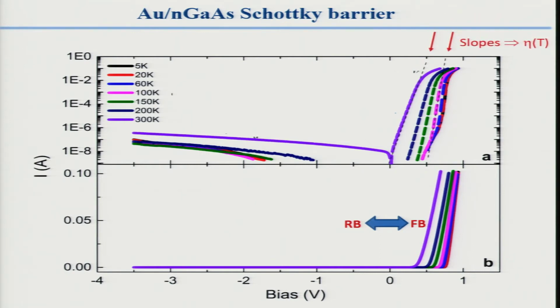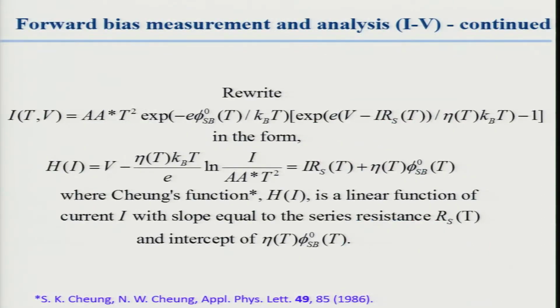These slopes from taking the log, this is logarithmic over a reasonable range, so we can extract from the slope of the log of the current versus the voltage the ideality, so we can measure that from the slope. And we get cut off by this series resistance limit. So you want the series resistance to be small. Otherwise, if it's large, you'll get cut off at a lot lower current. So we want low resistance. And so let me just show you a little bit about what we do with our analysis.